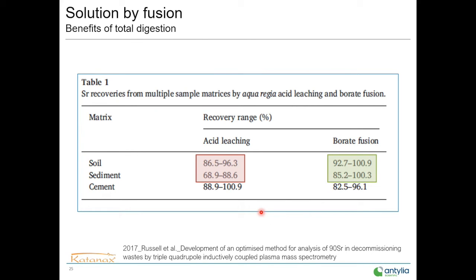On the solution side, the advantage of fusion will be mainly related to the efficiency of digestion compared to acid leaching. We have some data here that we took from a scientific publication, where we can see the difference of recovery between acid and borate fusion in different types of sample. You can see here that the recovery of strontium in soil and sediment is not as good as with borate fusion. The reason is that acid leaching will not completely digest the matrix, and some strontium will remain trapped in undissolved particles. In borate fusion, we reach a complete digestion, so we will have recovery that meets our expectation. The cement case was not illustrated here because if you look deeper in the publication, the post-operation and solution will influence the recovery. So we can see here that it's approximately equivalent.